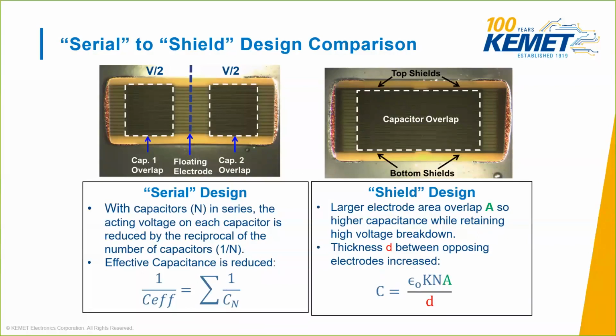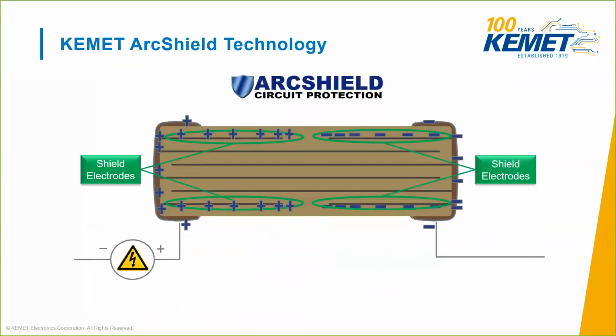Alright, so now how does this work? When a high voltage bias is applied to an ArcShield MLCC, a potential difference is established between the opposing termination and opposing electrode structure. But the electric field concentration is localized in the shield electrodes rather than the termination surface and respective first counter electrode. This minimizes the difference in potential along the surface of the chip and drastically improves the creepage distance capability of smaller case-sized devices constructed of high permittivity dielectric materials.